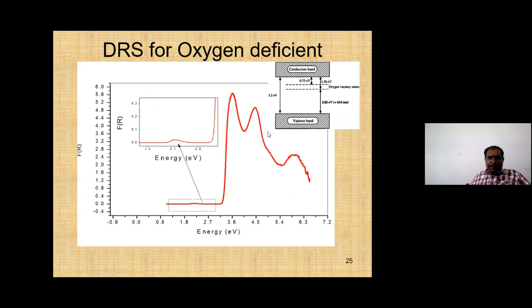So you can get that particular information, but how we define the band gap is the maxima of the valence band and the minima of the conduction band. The minima is a unique thing. So you cannot have multiple band gaps, but you can have multiple states present in the sample, which is essentially due to the electronic structure of that particular sample. In fact, I know there is a paper on LaFeO3, lanthanum ferrite, where the authors have shown, using density functional theoretical analysis, the presence of multiple states, and they have correlated these multiple states with the optical absorption spectra on their sample.